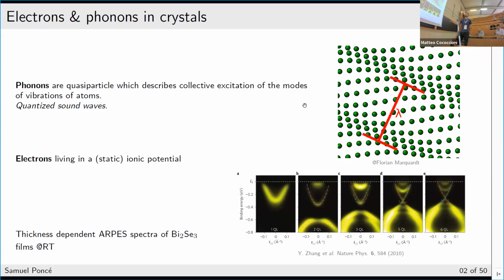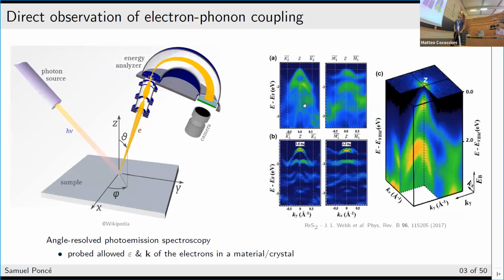But then if you start to look at them, maybe the best, most direct way is called ARPES, angle-resolved photoemission spectroscopy, in which you can see the energy of the electrons as a function of their momentum. This is really a powerful technique. So how does it work? You shoot photons on a sample, and thanks to the photoelectric effect, the electrons will be extracted from the sample with a certain angle and a certain energy. By recording that energy and that angle, you can reconstruct the band structure that you are computing with DFT and so on. So you really have these beautiful 3D maps of the energy as a function of the momentum of the electrons.